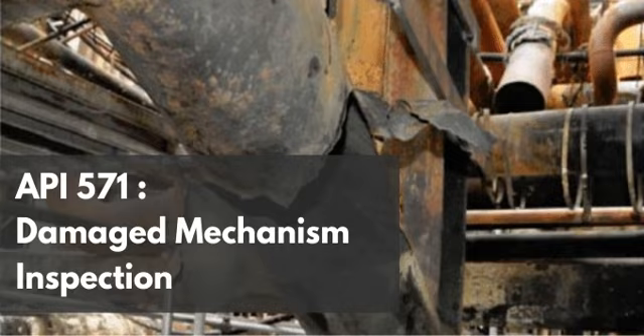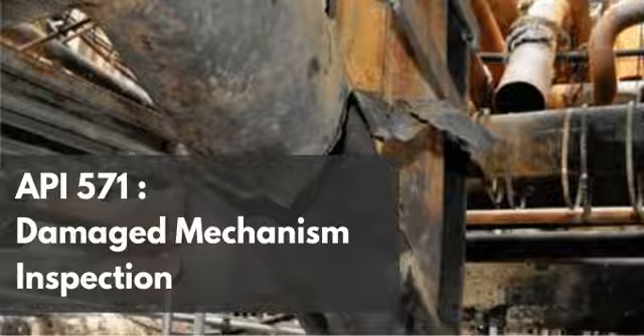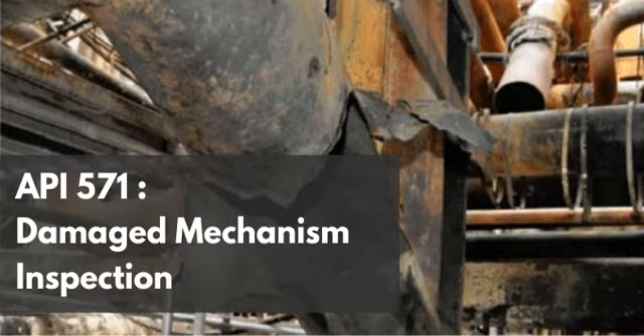If your NDT technician reports that you have a crack at a critical weld in a high-temperature amine line, your fitness for service assessment goes down a very specific, very urgent path. You are now dealing with fracture mechanics. Right. You're assuming the pipe is going to split open violently. Exactly. You are calculating crack growth rates, analyzing stress intensity factors at the tip of the crack, and evaluating the risk of sudden catastrophic brittle failure.